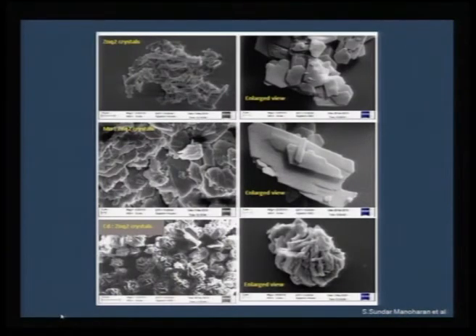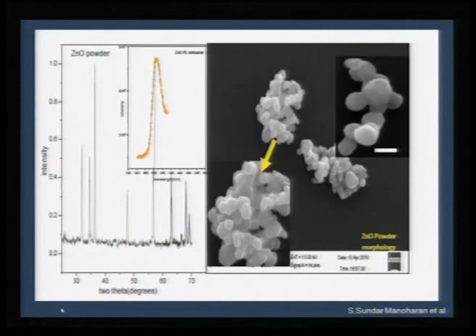And you can also see with just doping little amount of manganese or cadmium, the morphology of the zinc Q2 crystal changes abruptly with the doping. As you can see, this cauliflower sort of bundles coming out of cadmium substitution, platelet type coming out of manganese. Nevertheless, they do affect the surface morphology of the corresponding oxide. For example, zinc Q2, if I decompose, I get this sort of nearly spherical platelets of zinc oxide, and the beautiful emission characteristics of band to band emission is also seen here.